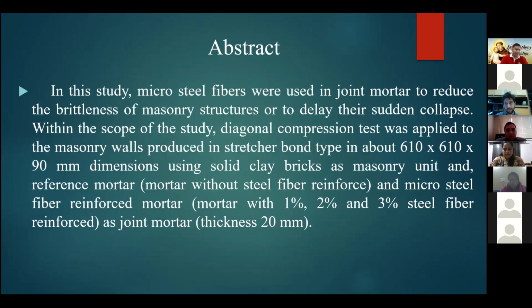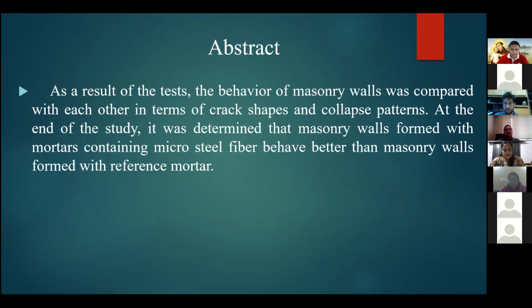In the study, microsteel fibers were used in joint mortar to reduce the brittleness of masonry structures or to delay their sudden collapse. Within the scope of the study, a diagonal compression test was applied to masonry walls produced in stretcher bond type, using solid clay bricks as masonry unit, and reference mortar and microsteel fiber reinforced mortar as joint mortar, with thickness 20 mm. As a result of the test, the behavior of masonry walls was compared with each other in terms of crack shapes and collapse patterns. At the end of the study, it was determined that masonry walls formed with mortars containing microsteel fiber behave better than masonry walls formed with reference mortar.